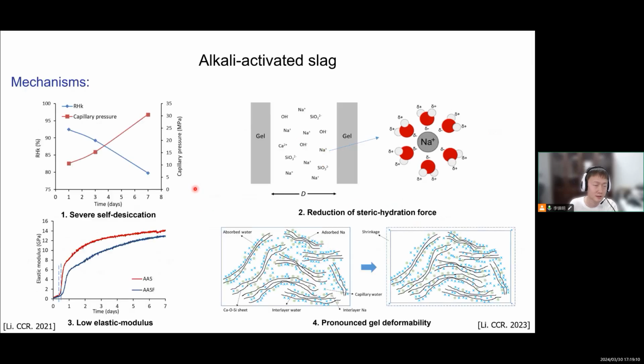So in summary, what are the mechanisms of the autogenous shrinkage of AAS? First is the big capillary pressure caused by self-desiccation. Second is the reduction of steric hydration force due to the consumption of ions. And the third reason is the low elastic modulus, actually. Alkali-activated slag or slag fly ash blended systems are not so hard or stiff compared to Portland cement. The elastic modulus is normally lower. And another reason is that it shows a very pronounced deformability. Actually, it is time-dependent behavior, which we call creep.